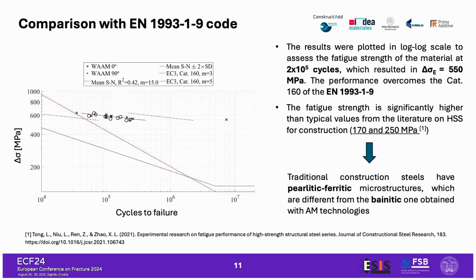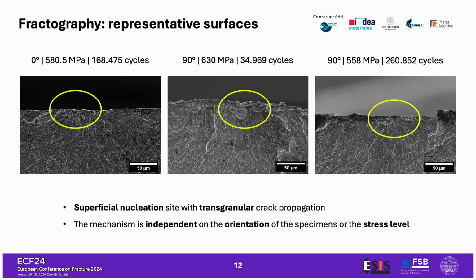Why this discrepancy? We linked this very different behavior to the microstructure, because usually steels in construction present a pearlitic-ferritic microstructure. And we now have from the additive manufacturing technology a very fine bainitic microstructure. So we think that, and also the Eurocode was based on traditional microstructure. So we think that this is the reason why the material properties are significantly different, and should present a significant difference also with respect to the Eurocode. These results say that this material is a promising steel for the construction sector. And finally, from the fractography point of view, we observed superficial nucleation of the fatigue crack with transgranular propagation. And what we observed is that the condition for the fracture nucleation is basically independent from the orientation and the stress level. So also this is important with respect to the anisotropy of the material.